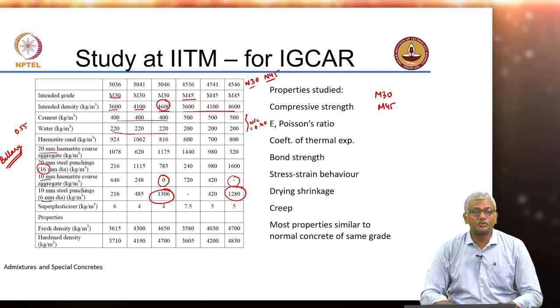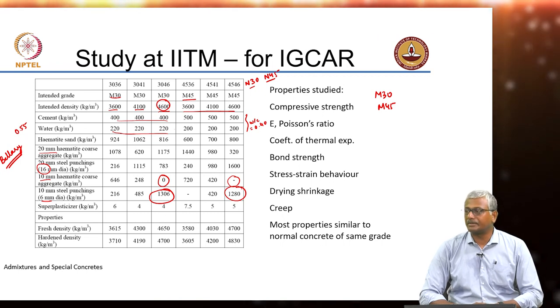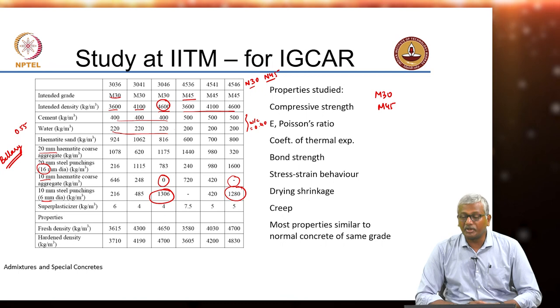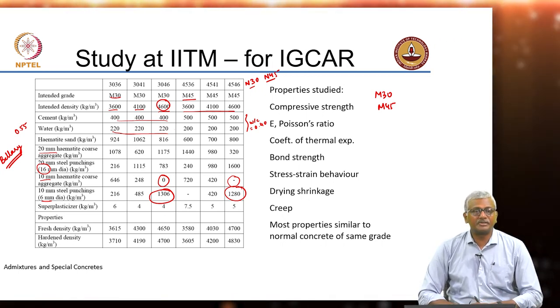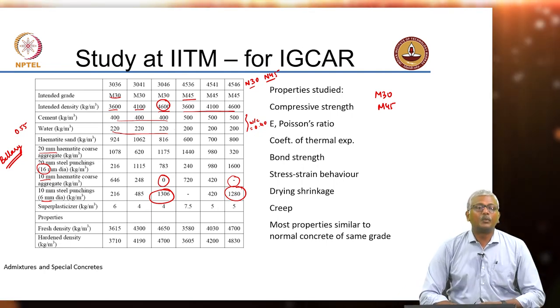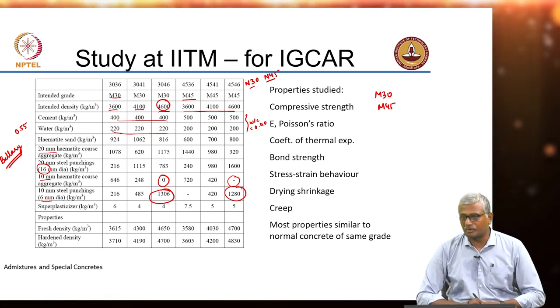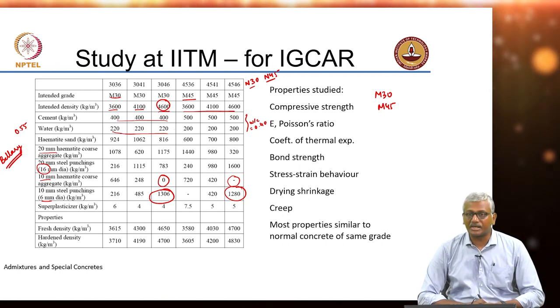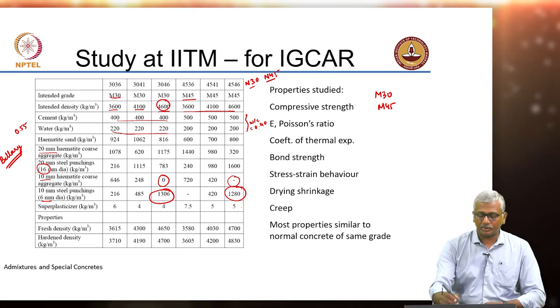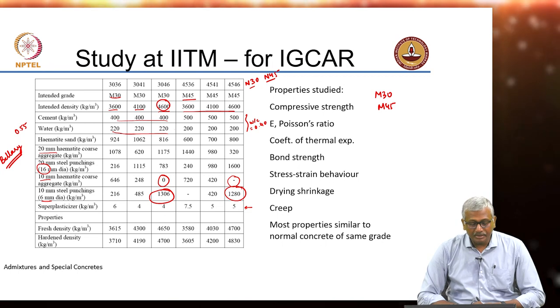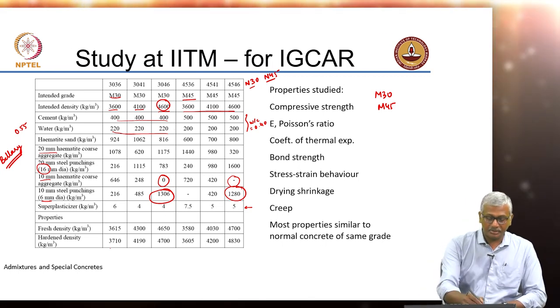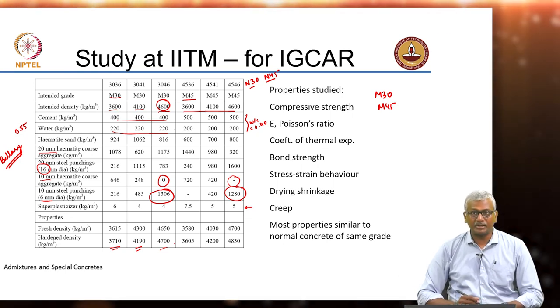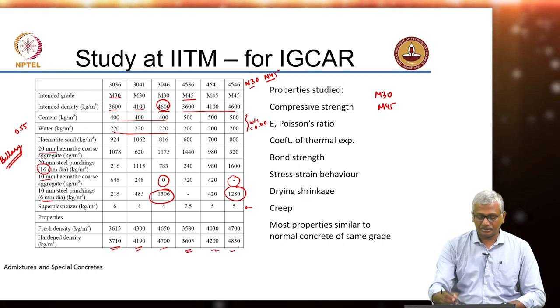Superplasticizer had to be used to make the mix compactable; pumping high density concrete is extremely difficult. There is ongoing research on pumpable high density concrete which would speed up construction significantly. In terms of densities, the required densities were easily obtained: a hardened density of 3700 was achieved for the 3600 target, nearly 4200 for the 4100 target, and 4700 for the 4600 target — approximately 100 kg/m³ more than required was actually achieved, and for some mixes it was almost perfect.